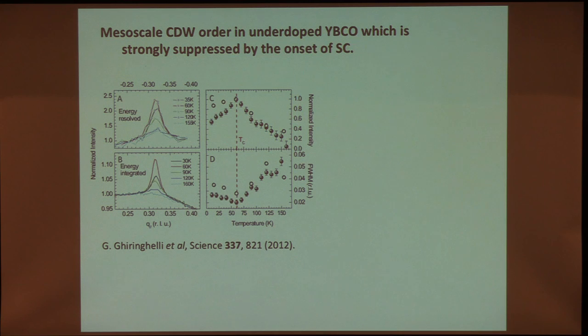Here's the beginning of the more modern inferences on this. This is YBCO, which is by general consensus the cleanest of all the high temperature superconductors. There's no particular metric of that. That's just a sociological fact. But anyway, it's accepted to be the cleanest of the high temperature superconductors. And here is an X-ray diffraction peak. This is actually an exciting new X-ray diffraction method called resonant elastic X-ray scattering.